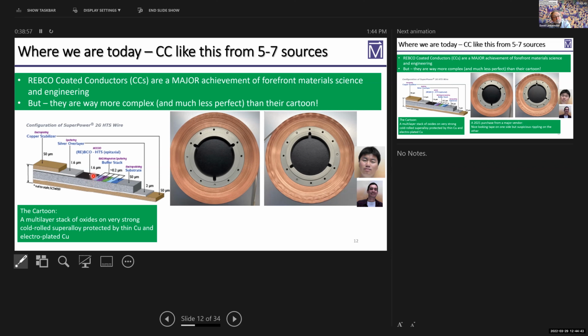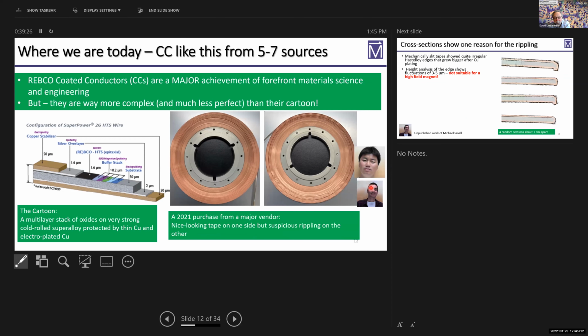And then you grow that layer on the top. You have to protect it because the YBCO is sensitive to the atmosphere, with sputtered silver. And then you protect the conductor even further with quite thick copper stabilizer. So this is the cartoon, this is the reality, and a couple of young guys, a Korean postdoc now on the staff, and a young recent MS graduate, Michael Small, who've been working on this.